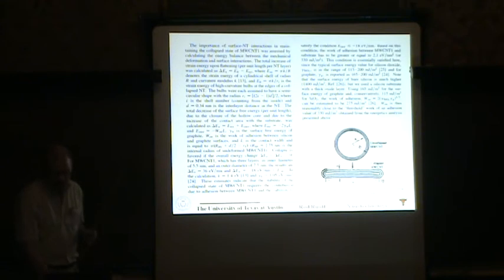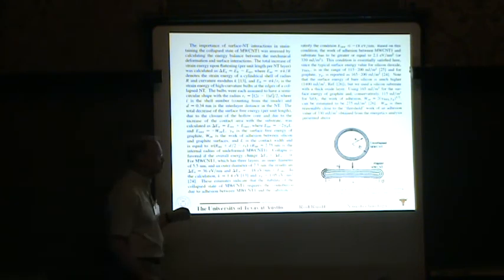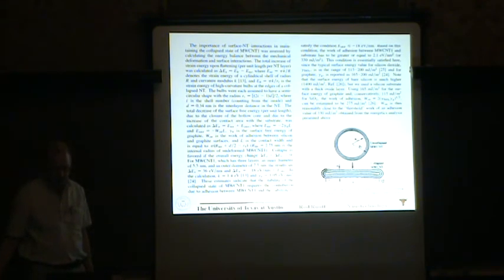Maybe I can jump ahead. Yeah. What happens is it collapses fully. And so actually just the height here almost immediately tells you the number of walls that you have, the number of nested, what would have been cylinders before collapse. And we have these bulb regions here. So the energetics analysis is really quite straightforward.